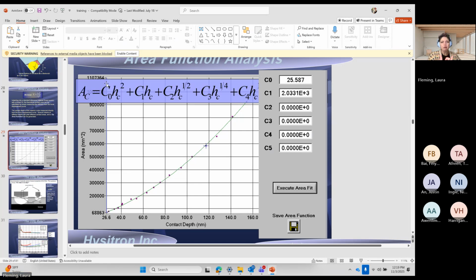function. On the other end of the spectrum, I have a customer who is testing cow eyeballs, which are very soft and squishy. She is typically going about 4 microns to 5 microns deep into that sample. At that point, the contact area is ideal. The Berkovich probe is going to be ideal at those deeper depths. If you think about the pyramid, the blunting only occurs here. If we cut it down here, it's going to act like that ideal Berkovich. She doesn't really need to worry about these other coefficients so much because of that.